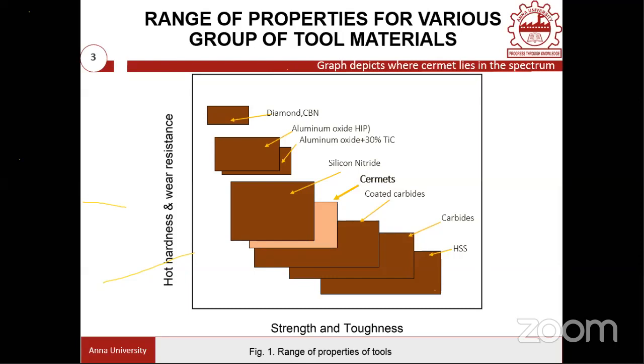Now the alumina, Al2O3, aluminum oxide, is employed as a cutting tool material because it has good oxidation resistance and also chemical inertness, with a still high hardness value compared to even carbides and CERMETS. Therefore, pure alumina, also alumina plus 30% TiC. In addition, they are making some sintered ceramic composite body, which can be employed as a cutting tool material. So now we have plenty of cutting tool materials, starting from high-speed steel to diamond.